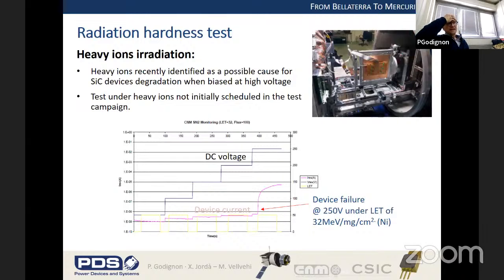However, during this development phase, NASA published a paper showing that we could have an issue with heavy ions on silicon carbide devices. So it was really new information, and this test was not originally scheduled in the test campaign, but we finally decided to test our devices under heavy ions. And effectively, we have seen a kind of premature degradation, a breakdown at 250 volts, while our devices target 300 volts, under a relatively medium LET, so energy dose, of 32 of heavy ions. So it confirms that effectively silicon carbide is quite sensitive to heavy ions.